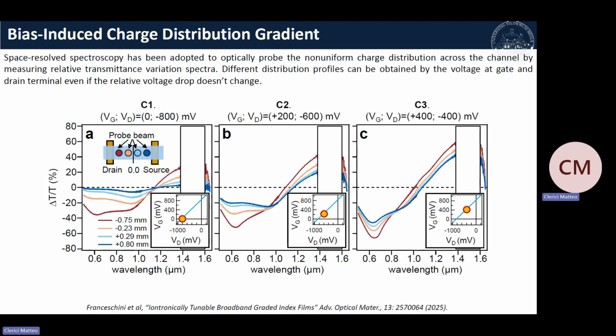What we found was that, keeping the same relative voltage drop of 800 millivolts between the two electrodes, but adopting a different configuration, we could realize different transmission profiles, therefore corresponding to different permittivity profiles along the channel. We probed from the source to the drain, and we saw that the transmission was going down. In this particular configuration, where the two electrodes have equal and opposite voltage, we can modulate transmission up to 60%.